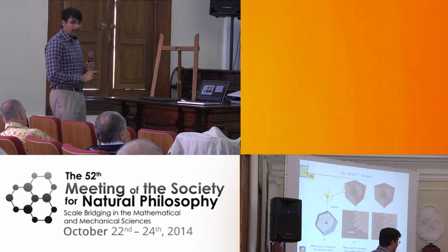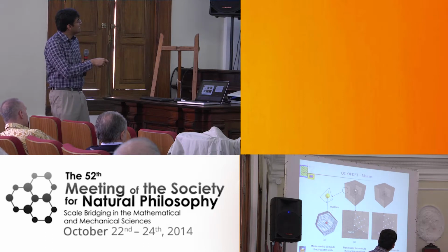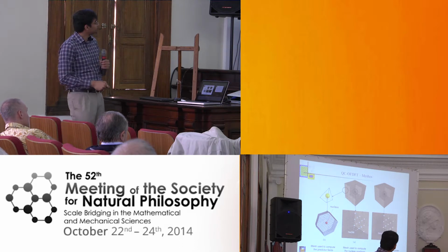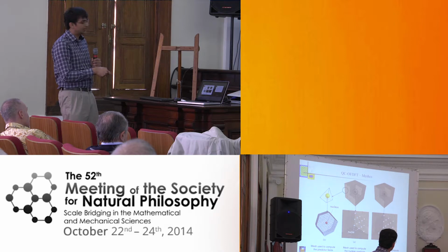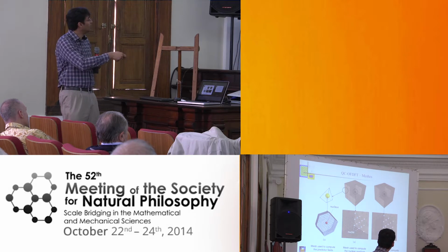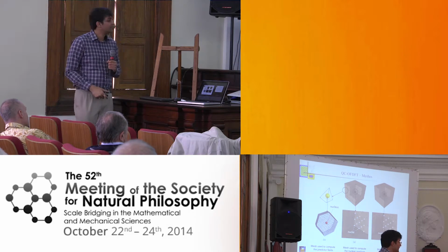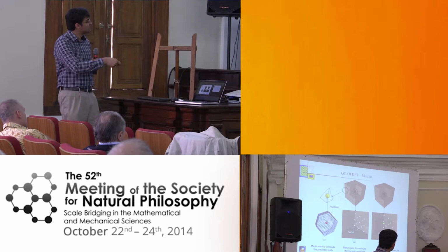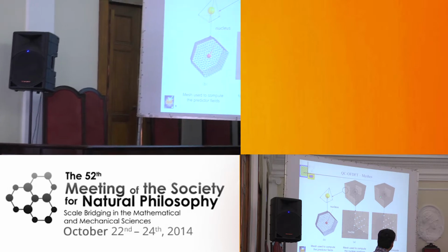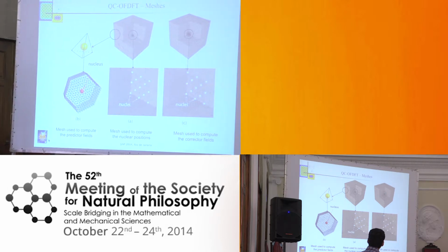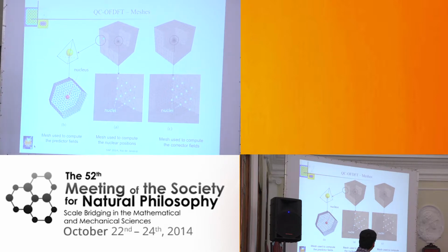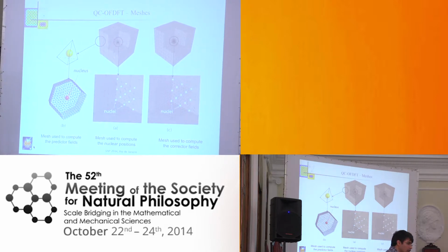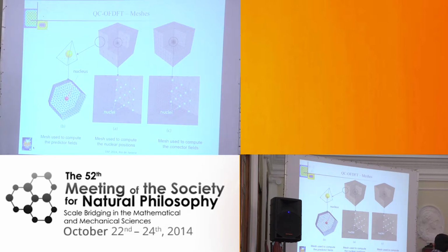And here is the hierarchy of triangulations that we use. Let's say that this is our simulation domain, and we have a defect at the center over there. So this is the mesh which captures the displacement fields. It has full atomistic resolution close to the defect core, and it coarse-grains far away from the defect core. The corrector fields are computed on a mesh, which is a subdivision of this mesh, which has subatomic resolution close to the defect core and coarse-grains to become superatomic far away. And the predictor fields are computed on unit cells in each of these elements using the Cauchy-Born approximation. So these are the hierarchy of the meshes that we have.